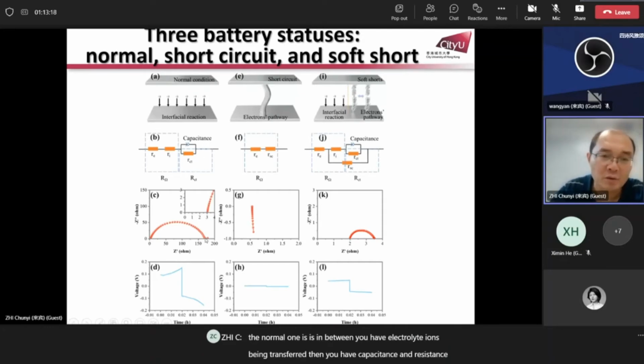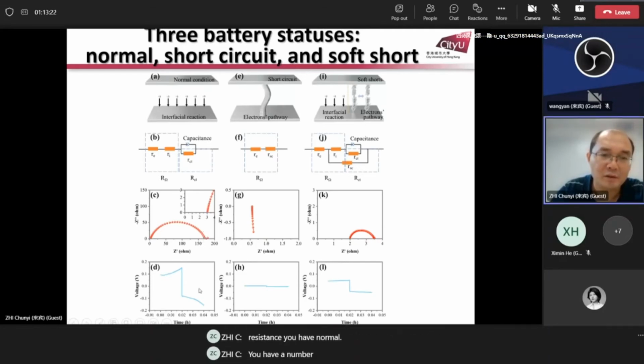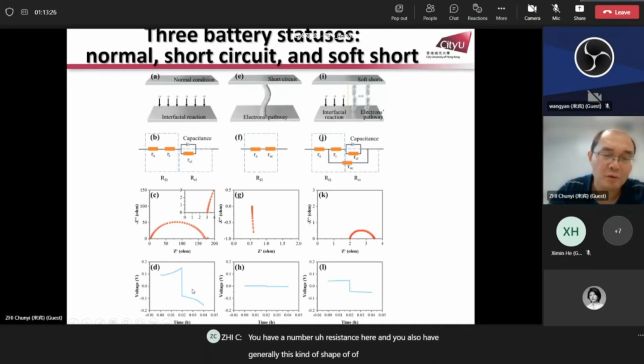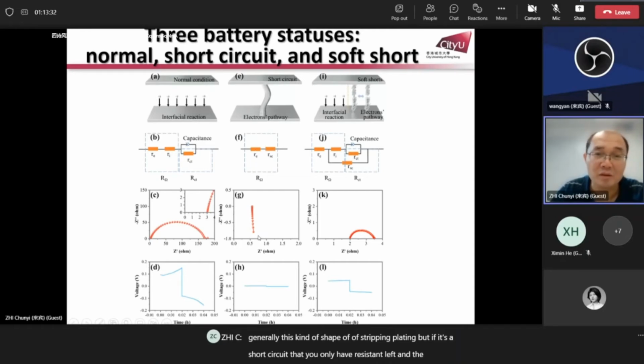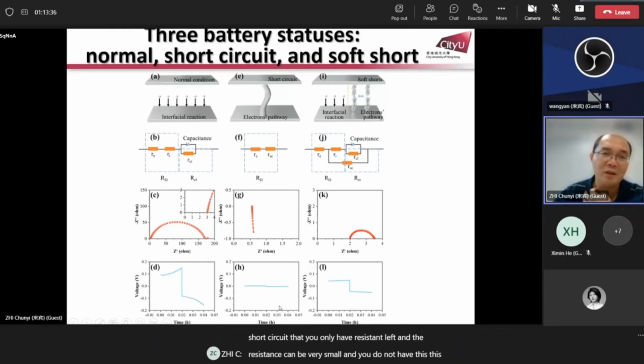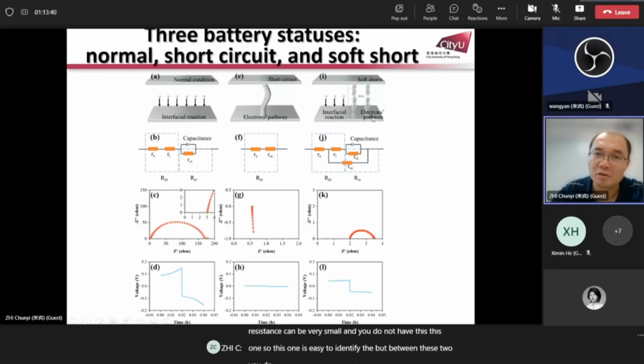You have a normal resistance here, and you also have generally this kind of shape of stripping and plating. But if it's a short circuit, you only have resistance left, and the resistance can be very small, and you do not have this one. So this one is easy to identify. But between these two, you do have soft shorts.